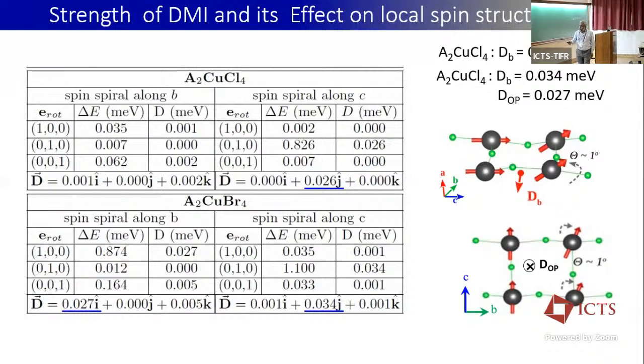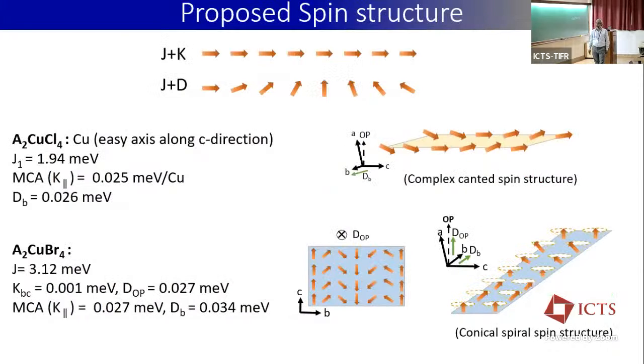And if you have an out of plane D, what will happen? It will try to cant into the BC plane. So this is how the in plane D and out of plane D will affect the spin direction. Now, based on this, we proposed a structure, because it is very difficult to do any neutron diffraction measurement to test whether it is really the spin structure, and atomistic spin dynamics simulation has to be done. But naively we can understand from these numbers that your J1 is roughly 1.94 milli-electron volts,